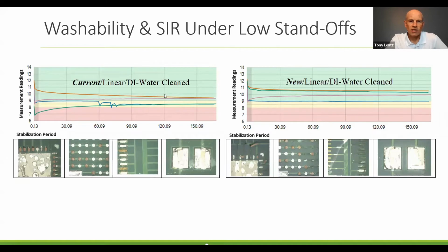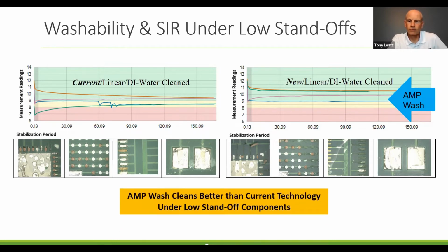So the current solder paste had pretty low SIR numbers even after cleaning, whereas the new solder paste, Amp Wash, under the same conditions, all the resistance values were above 10 to the 9th and much higher than that. So quite a bit better SIR results after cleaning under low standoff components. And that was one of the other major goals for this product, to enable improved cleaning, especially in tight gaps.